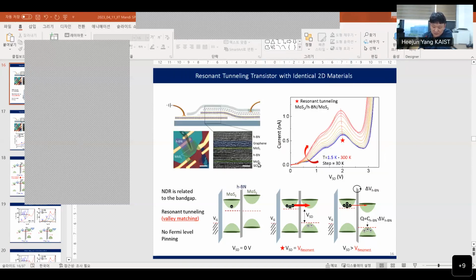My initial idea was to see some Moire effect, but it was not that clear. Maybe the Moire feature is also reflected in our device result. For your information, here we have hBN MoS2, hBN MoS2, so we have some Moire band here. This transport IV is a very simplified model of only the conduction and valence band of the MoS2, but we should draw some additional bands from the Moire pattern. But for now, we have only two clear features, this shoulder and something. So it was enough to consider this band.